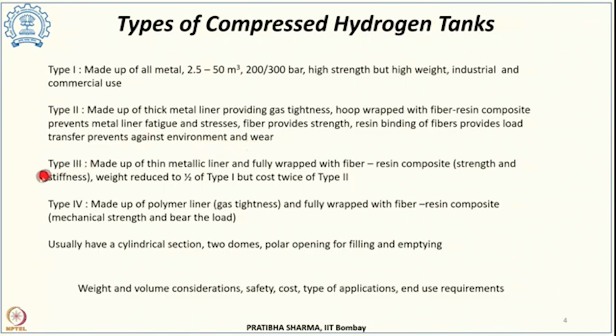The third category is type 3 tank, which is again made up of an inner liner which is metallic, but a thin inner metallic liner, and instead of partially wrapping with the fiber resin composite, it is completely wrapped with fiber resin composite. Now again the liner provides gas tightness, while the wrapping of this fiber resin composite provides strength and the required stiffness. As we move along from type 1 to type 2 to type 3 and later to type 4, the weight of the tank reduces, but the cost increases. So if we see type 3 tank, their weight is half of that of type 1 tank, but the cost is twice that of type 2 tank, and that is the major drawback.